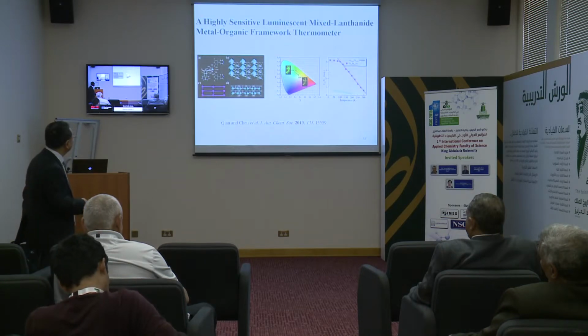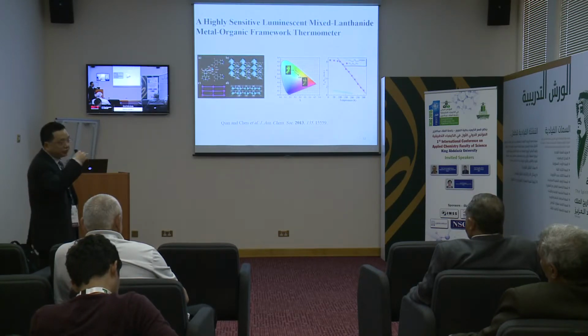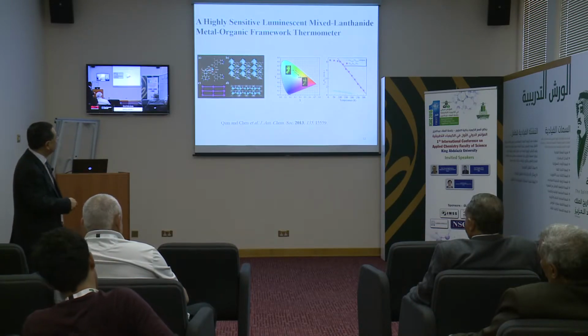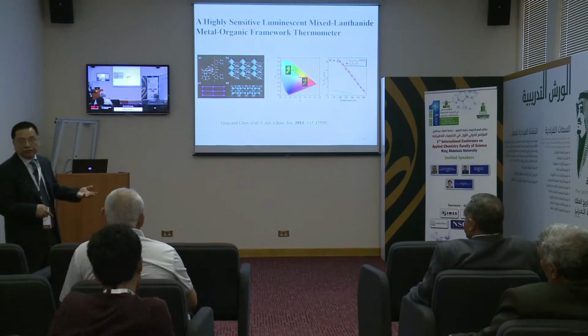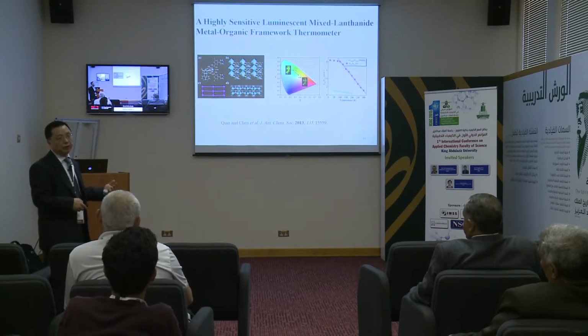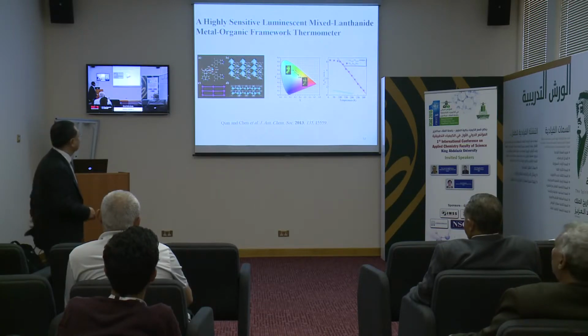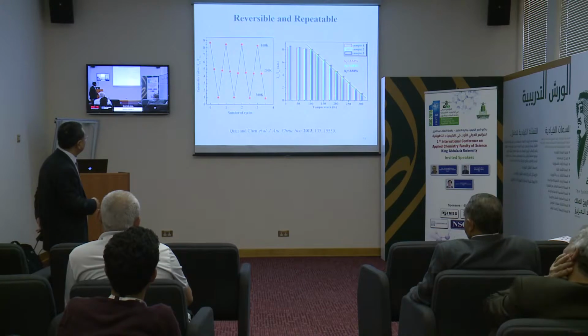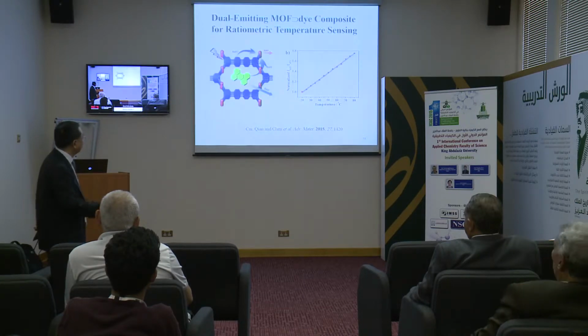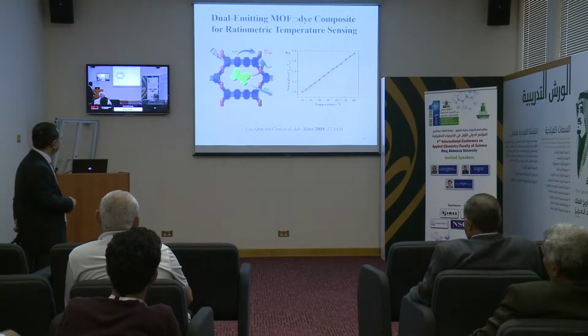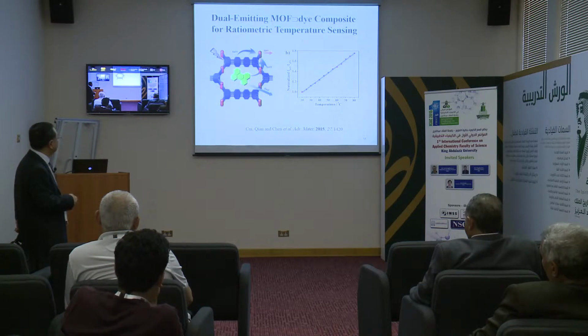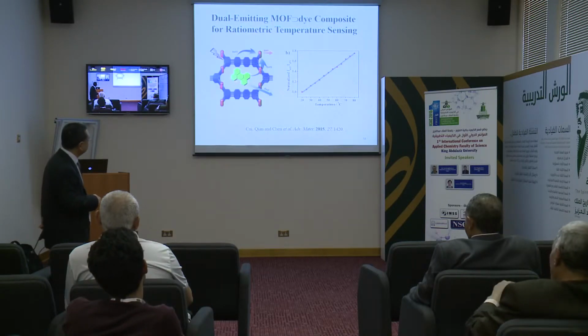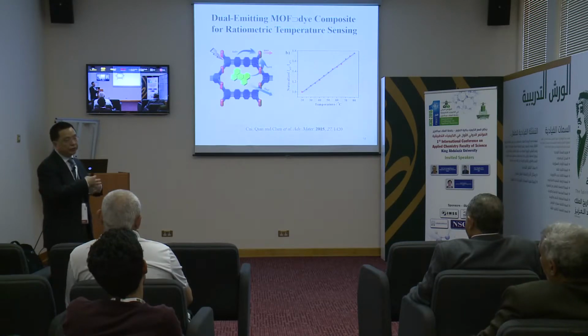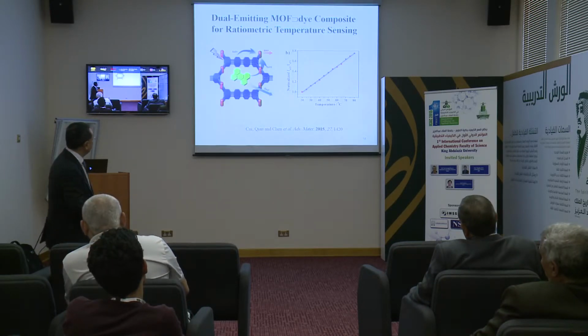And furthermore, we can use different organic linkers. So the transition, T1, S1, this energy transfer can be tuned, so the sensitivity can be significantly enhanced. So this is quite an interesting example. This is not a beautiful metal organic framework, but useful for certain applications. And this is quite robust. We can go down, go up, and the sensitivity is still very stable. We can also incorporate these guest molecules, with a different center. One luminescent center for our metal organic framework, and another center for our gas molecule. So we can still use these 2 luminescent centers to get a reliable thermometer.